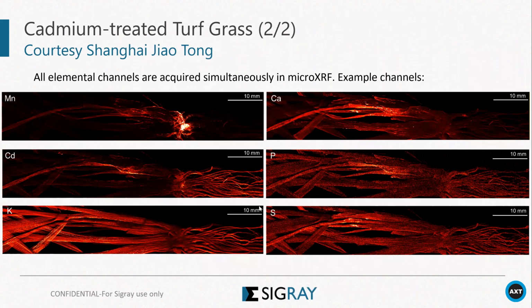Another one is a plant example showing the capability for plants. As you can see, this is scanned over a huge area: we scanned about 70, 80 millimeters long in one direction and about 10 millimeters in the other. You can see the root, and there are several elements shown here: manganese, calcium, phosphorus, sulfur, and cadmium. They're mainly interested in seeing cadmium uptake for this particular plant. This one is done in fly scan at 10 milliseconds per point.